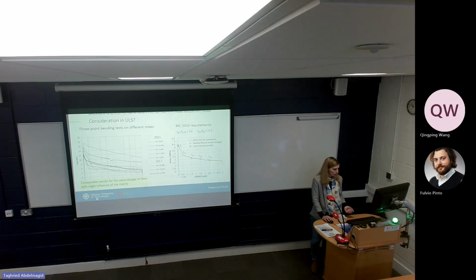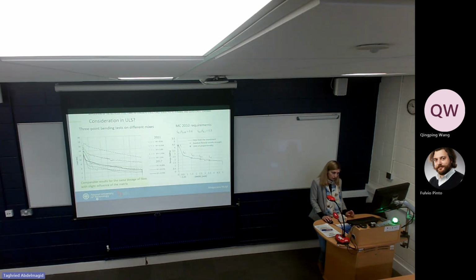And now, as I said, we have the improvement, but how big is this improvement? Can we use it or not? So we have to look at the requirements from Model Code 2010. Generally, in fiber reinforced concrete, we first consider the maximum load at the limit of proportionality, when it starts to crack. And then we have the values of the stress that the beam is still able to carry for a given crack width. So we have 0.5 millimeters, then 1.5 and 3.5. So we have to check if it's still able to carry some loads.